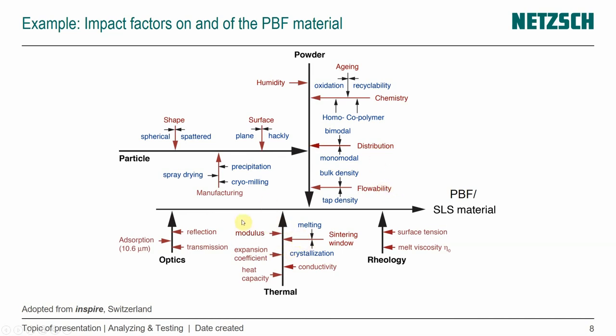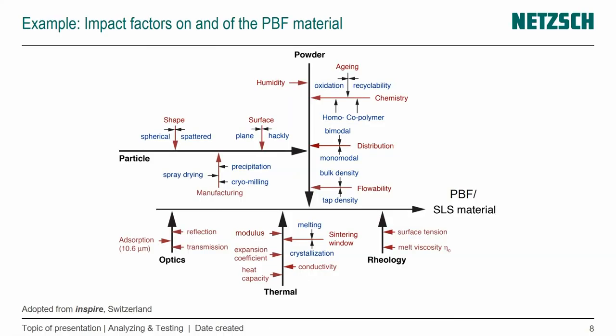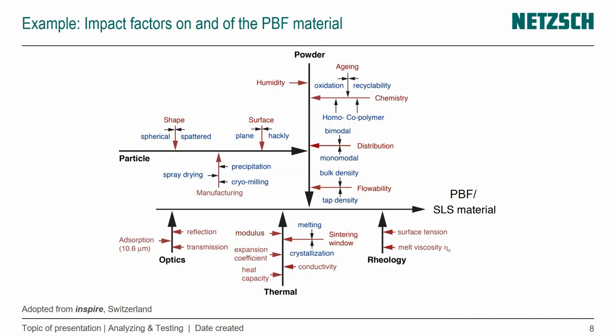From the bottom of the schematic you see aspects of the properties — like what optical properties there are: what's the absorption at the wavelength of the laser, how much does it reflect, how much does it transmit, how easy is it for the energy to penetrate to a certain depth. The thermal properties: what modulus do we have as a function of temperature, the expansion coefficient, how much does it expand and shrink, the melting behavior, the conductivity — how far is the energy from the laser conducted into the melt and also into the solid powder surrounding it. And the rheology — the melt viscosity, for example, how well do the particles coalesce once they're hit by a laser.